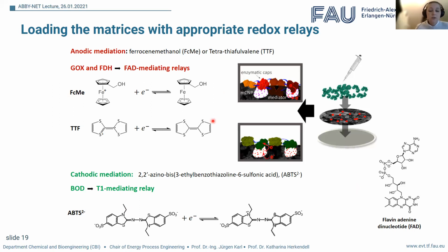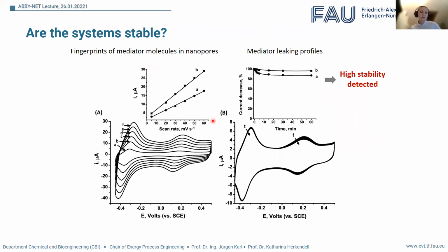This we characterized then electrochemically, and you can see here just as an impression the different stability measurements that we made, for example, at different scan rates to analyze how the peak currents relate to the different scanning speeds of changing the potential towards the electrode, which means you would actually scan from a low voltage to a high voltage and back and see how reversibly the redox interaction of the molecules on the surface were.